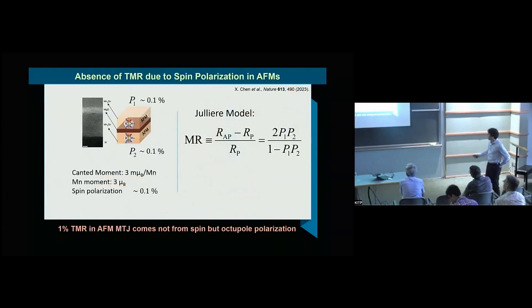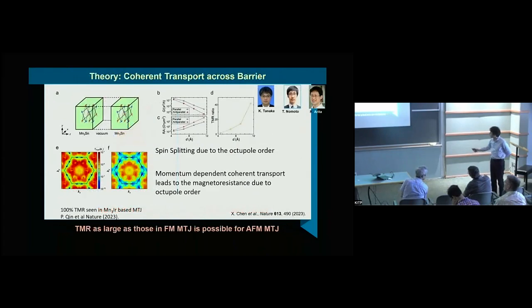I just wanted to make the point that this cannot be simply understood by spin polarization. Of course, as I said, there is a small moment, magnetization of about 3 milli-mu-B, spin polarization of the order of 0.1%. So a simple-minded calculation tells you that the MR due to spin polarization should be 10 to the minus 6. So the observed 1% TMR cannot come from the spin polarization, but from the octopolar polarization. And indeed, a theoretical calculation has been made and found that 100% or maybe even larger MR is possible due to the large spin splitting from this octopolar order, and the transmission along the direction perpendicular to this electrode is coherent and can be momentum dependent, and that can lead to the magnetoresistance.